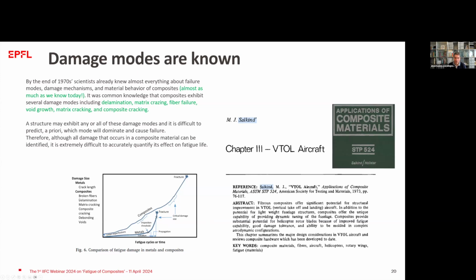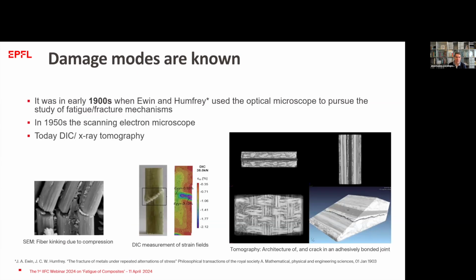While for composites, we have a lot of different failure modes that do not appear individually, but they are interacting, and this makes the behavior of a composite material much more complicated than the behavior of metallic components. So this investigation about failure modes started also early. In the 1900s, we had the first use of the optical microscope to investigate fracture mechanics characteristics. In the 1950s, we had the scanning electron microscope, and today, of course, we use DIC, X-ray tomography, thermographic cameras to investigate all these effects in metals and, of course, in composites.